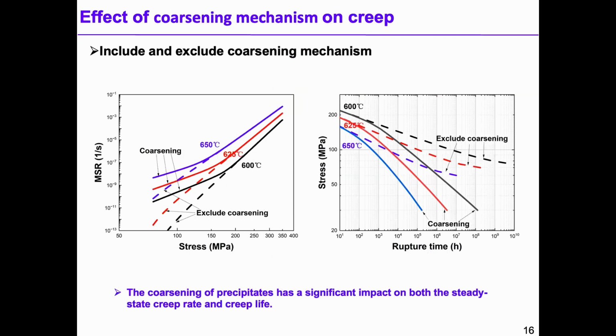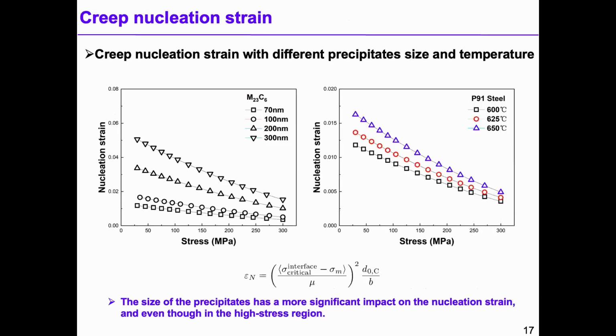And then we further investigated the effect of coarsening mechanism on creep. The solid line includes the coarsening mechanism, and the dotted line excludes the coarsening mechanism. We can see from these two pictures, the coarsening of the precipitates has a significant impact on steady creep rate and the rupture time. We use this formula to calculate the creep nucleation strain with different precipitate size and temperature. From the two pictures we can know that the size of the precipitate has the most significant impact on the nucleation strain.